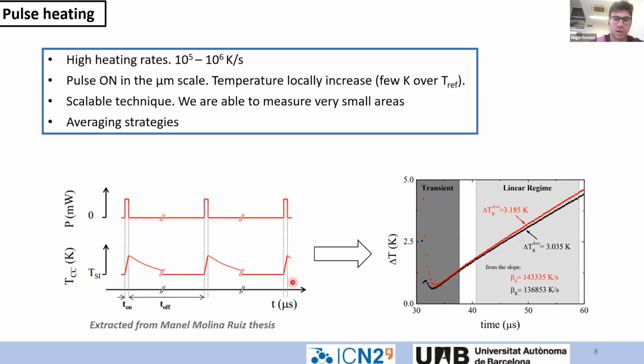So by doing this, we can access the resistance and the temperature of our calorimetric cell, which is the part of the cell that we are heating. We can extract the resistance and the temperature, and then simply take the heat capacity. The most important thing about this technique is that it is a scalable technique.